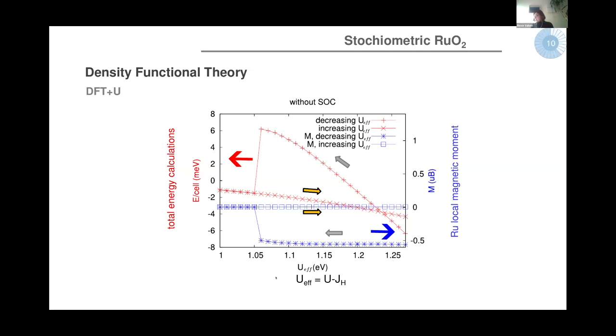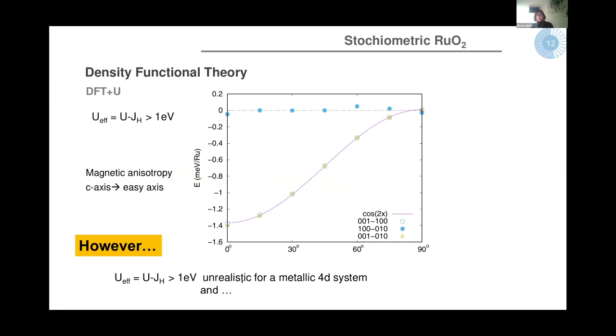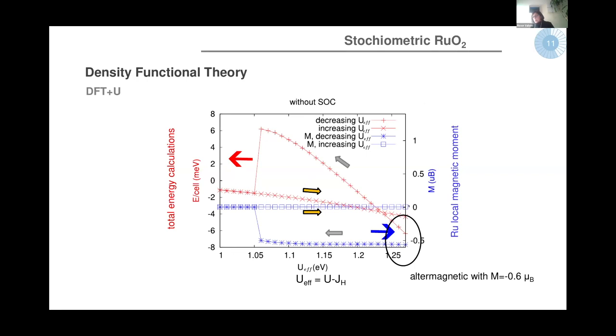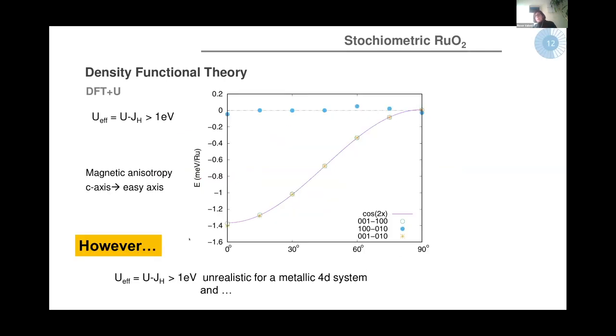Moreover, maybe what I should say is that in this altermagnetic solution with these very large U values, DFT indeed also predicts the direction of the magnetic moments, which is the one also claimed in the experiments, which would correspond to having the magnetic anisotropy along the z-axis, or basically the magnetic moments oriented along the z-axis. So, as I was mentioning, this U effective is very unrealistic.